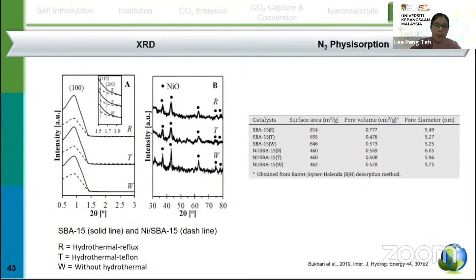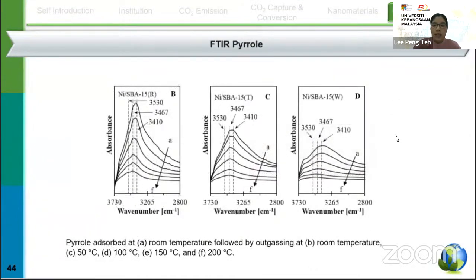We also explored different hydrothermal treatment techniques. For example, we have reflux hydrothermal, Teflon hydrothermal, and W, which is without hydrothermal. In this study, we carried out different kinds of characterizations. We carried out XRD and nitrogen physisorption. We also determined the basicity properties by using FTIR pyrrole. If you don't know what FTIR pyrrole is, basically there will be a peak at 3467 over here, which shows the basic peaks of our samples. The higher the intensity of the peak at 3467, the higher the basicity exhibited.